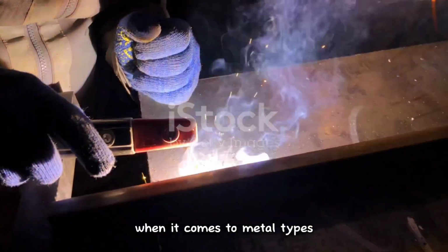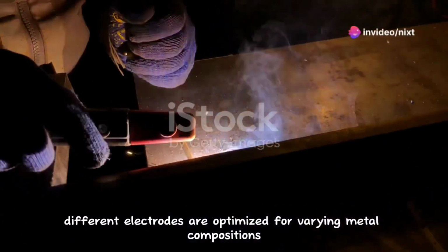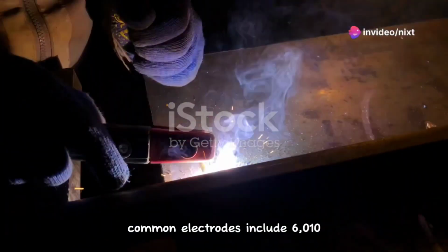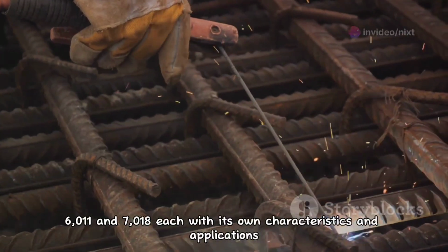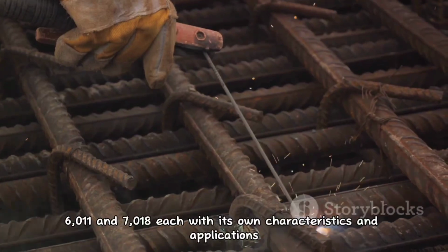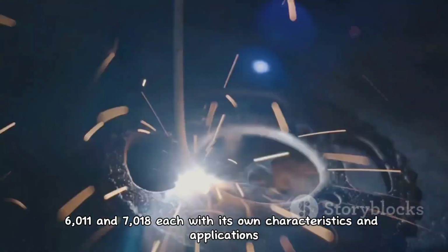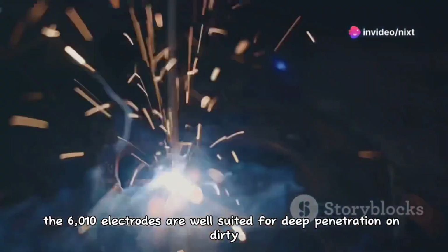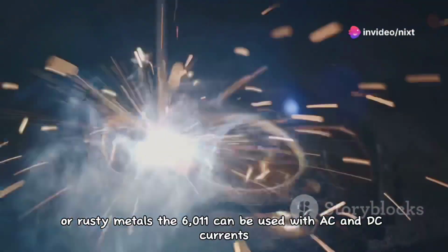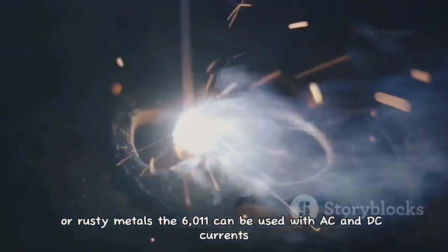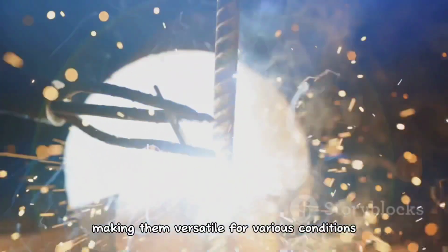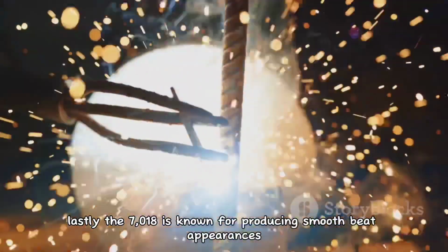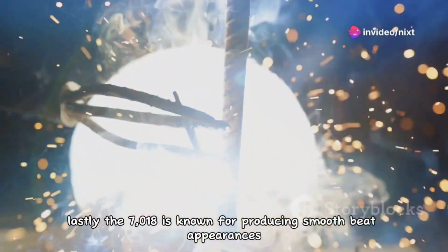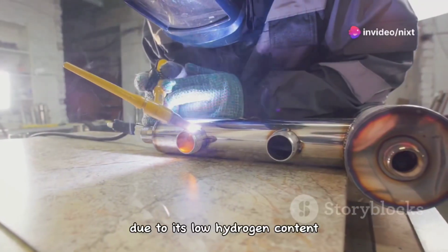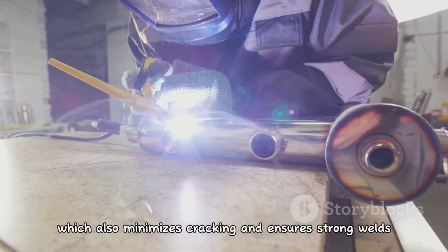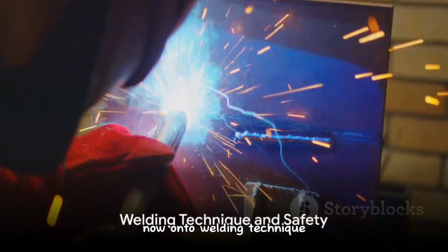When it comes to metal types, different electrodes are optimized for varying metal compositions. Common electrodes include 6010, 6011, and 7018, each with its own characteristics and applications. The 6010 electrodes are well suited for deep penetration on dirty or rusty metals. The 6011 can be used with AC and DC currents, making them versatile for various conditions. Lastly, the 7018 is known for producing smooth bead appearances due to its low hydrogen content, which also minimizes cracking and ensures strong welds. Now onto welding technique.